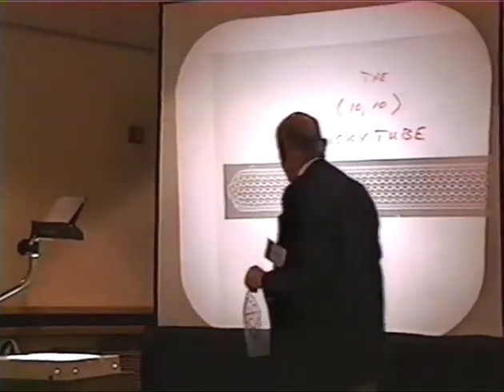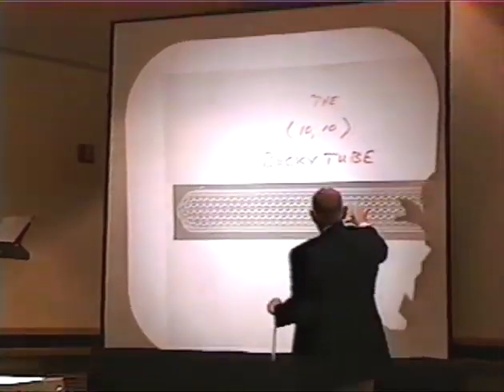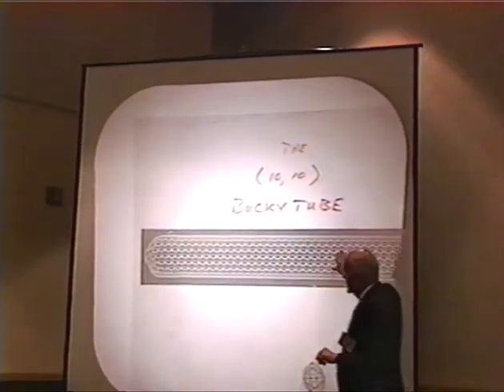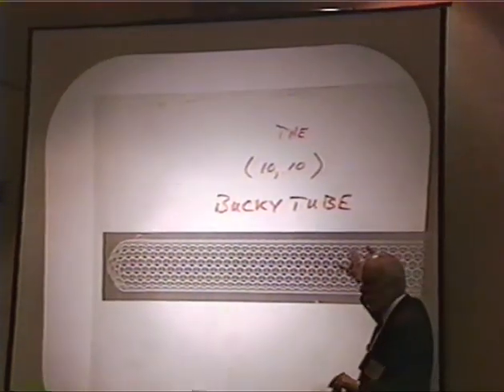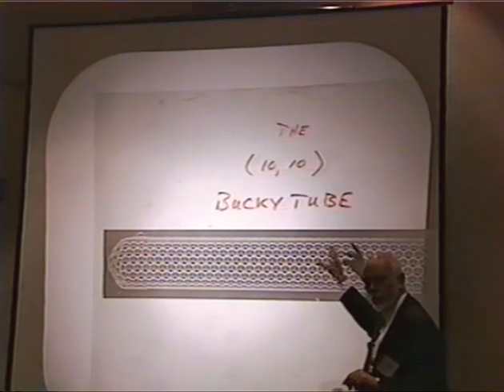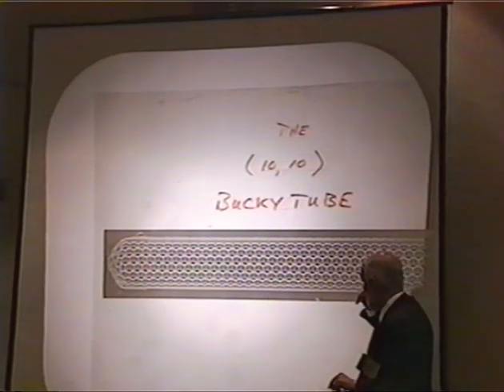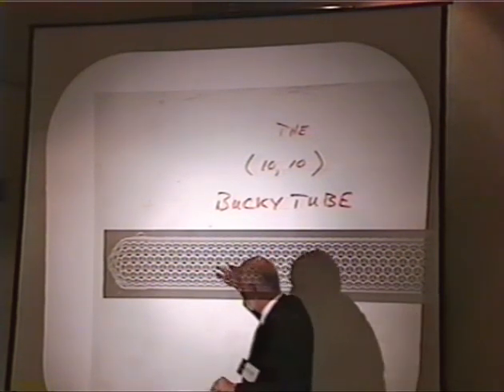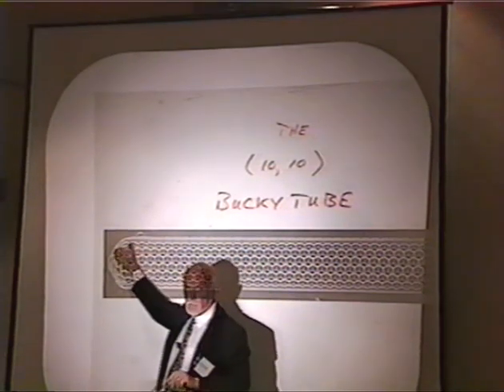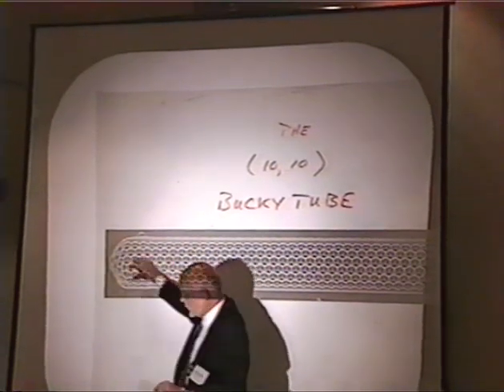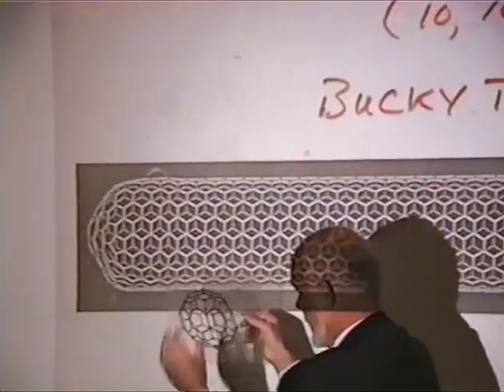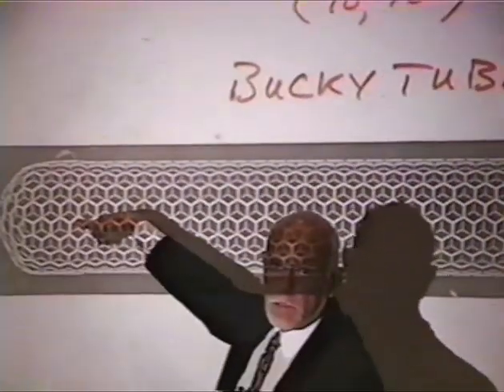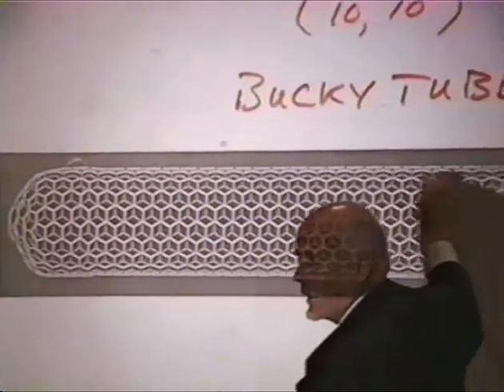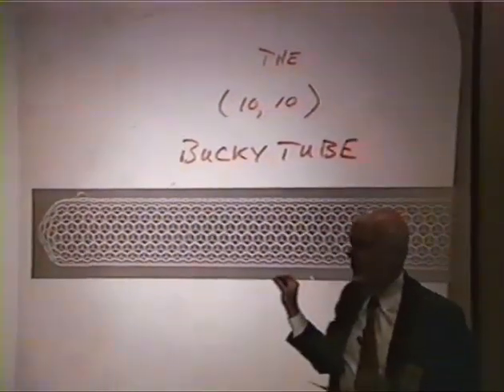In any event, this tube, which for fascinating reasons turns out to be the one that grows so preferentially in the gas phase, happens to be the one whose end cap has half of C240, which means a buckyball, or C70, which has its end cap being the same as the buckyball, conforms to the inside surface of this perfectly and would slide along the tube like a BB.